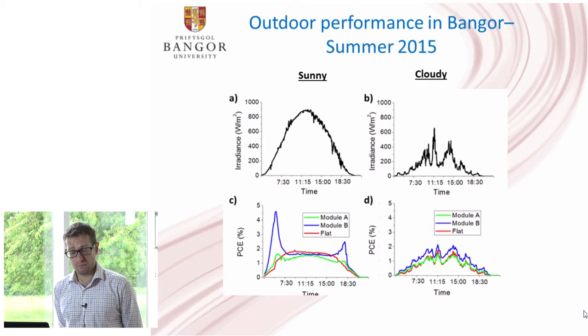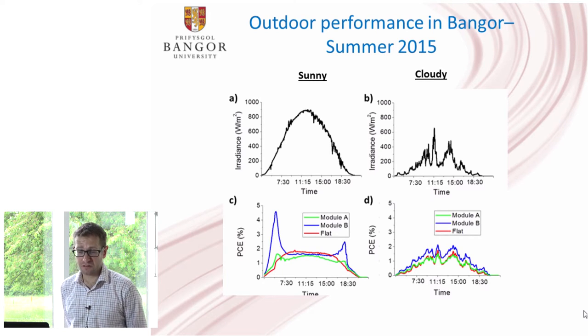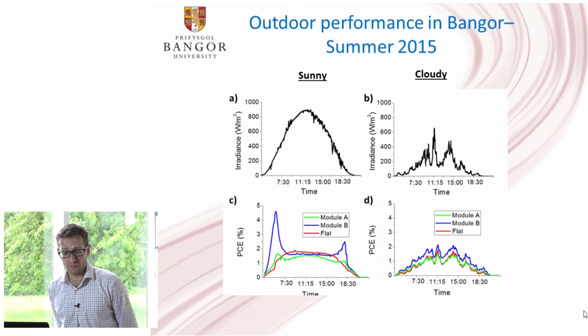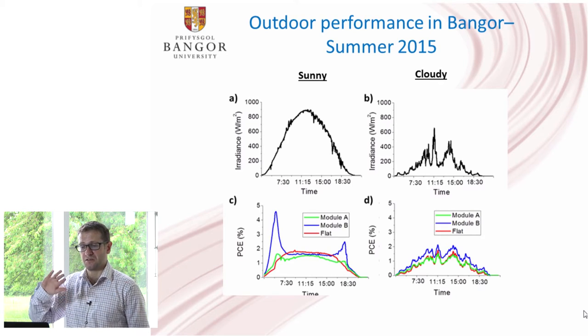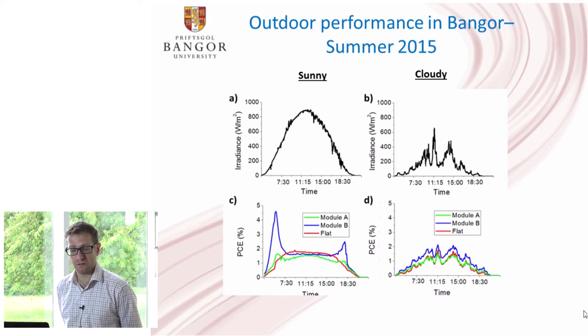Both of this set of data was done in the summer of 2015. Compare first of all the sunny performance. So the sunny performance in Bangor means we get up to an irradiance of around about 1,000 watts per meter squared. So for our flat module, we get the expected trend where effectively our PCE is relatively flat from around about 8 o'clock in the morning up until about 5 p.m. in the evening. But with our three-dimensional module, what we see is a big increase in efficiency in the early morning, so around about 7 a.m. and a big increase around about 7 p.m.